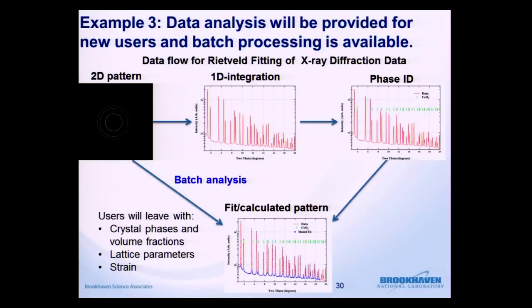So this is the last example that I'll show. And this is an example of how we'll be using automation of data analysis to increase the amount of throughput and what the implications of being able to do that are on our system. So this is the 2D diffraction pattern that you collect at the detector. This is then integrated. Again, these peaks are the fingerprint of the material. And we do a phase ID, and then we fit the pattern. From the fitted pattern, we are able to get the crystal phases, the size of the unit cell, the size of those lattice parameters, and also the strain.